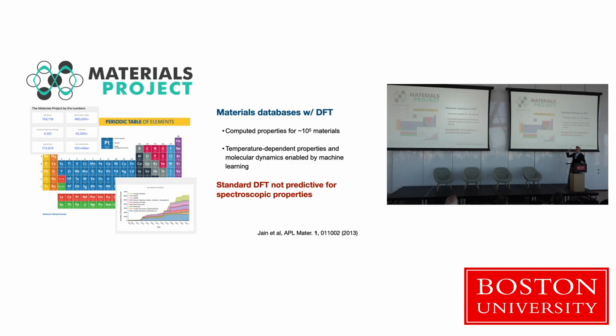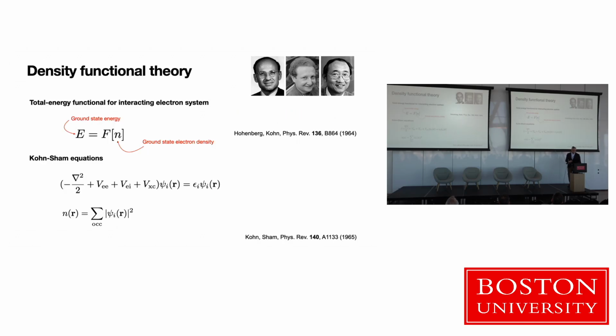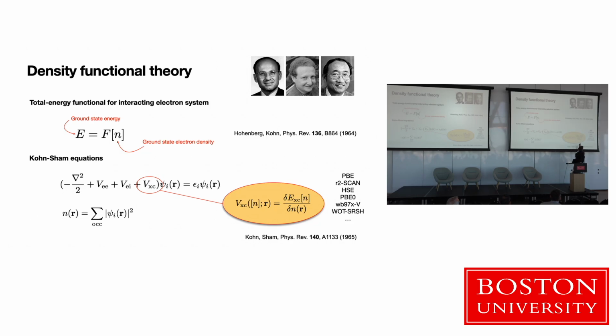So I think there's a real opportunity here. This is not necessarily a deficiency per se, in that you have to start somewhere, and they've got a terrific data set here, but that's a deficiency. And so one of the things we wanted to do is use density functional theory to predict some of the things that I just showed that were predicted with beyond-DFT methods. I'm not going to go through a reminder of DFT for you, but basically it's a way of getting the ground state energy as a functional of the electron density, but the functional isn't known and it's approximated. And that approximation leads to this alphabet soup of PBE and other things.